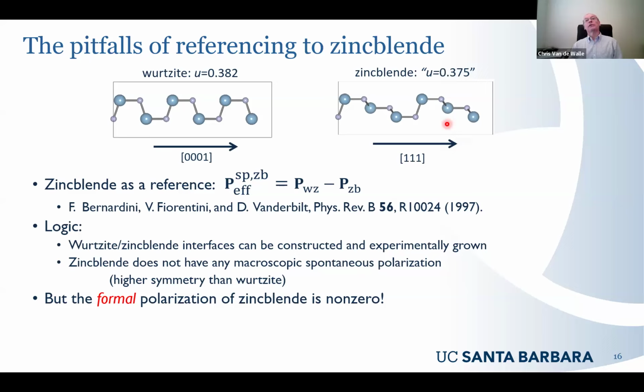Unfortunately, this issue of the spontaneous polarization being zero is true at the macroscopic level, but it's not true for the formal polarization of zinc blende. So if you use that formula that I showed to you for calculating formal polarizations rigorously, and you apply it to a zinc blende structure, you find a non-zero value. Now, people are often confused by this. They say, well, how is it possible that you can find a non-zero formal polarization for a material that macroscopically doesn't exhibit any polarization? The reason, again, goes back to this more complicated way in which we need to define polarization.